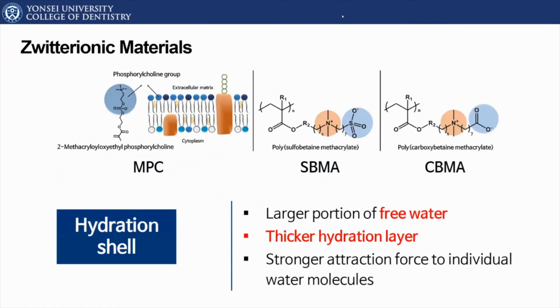There are three major zwitterionic materials that have been investigated and used, or applied even. The MPC is perhaps the older and commonly used zwitterionic material, and the others are SBMA and CBMA, which are meant to be cheaper and more recent in terms of the advancement of these zwitterionic materials. All these materials have polar or non-polar regions, or cationic and anionic regions, with overall charge being neutral. Because of this unique structure, a hydration shell is formed on those particles, which means they have a large proportion of free water that forms a thicker hydration layer, and that provides a stronger attraction force to individual water molecules.